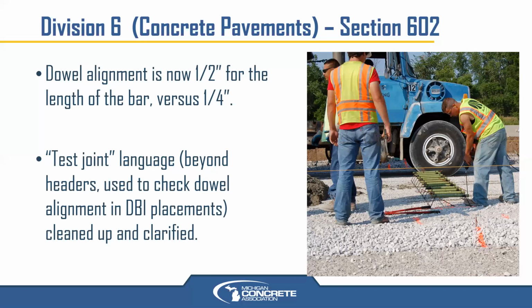Second thing, the test joint. This is for slip form paving jobs where they utilize a dowel bar inserter, which is not being utilized on this project you see. They're using dowel baskets on this project pictured. But if the contractor elects to use a dowel bar inserter with loose dowels and has this piece of equipment incorporated into the paving train, MDOT requires them to do a test joint periodically on each bound, a certain number of times, depending on the size of the job, where they actually pave out beyond where they're going to saw back and create their header for the next pour.